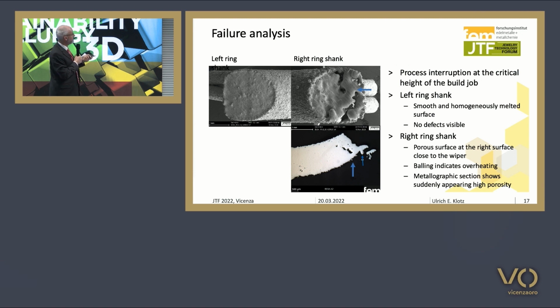So we get little droplets of melt. We get a large porosity. If we look at the cross-section in the metallography, we see very large pores. And this is a clear indication of overheating.